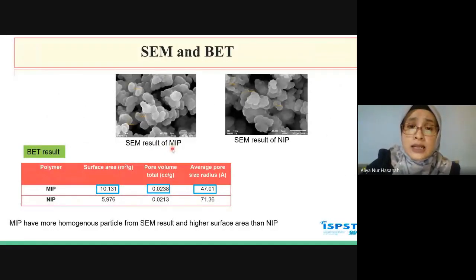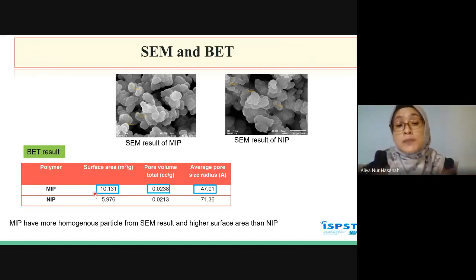This is the result of the scanning electron microscope and BET. From the scanning electron microscope, you can see that the MIP has more homogeneous particles than NIP, and the surface area is also larger, so we have more space for adsorption than NIP.